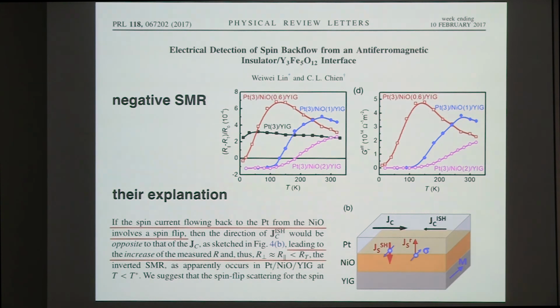Another thing is that we know them very well, they compete with us. So they actually at the same time produced the same result. Basically, this data tells you the same story, the same phenomenon I just showed. But actually, I want to criticize them, and very bravely in front of this camera. Yes. I think that this title and the explanation is far from satisfactory. The reason is that they think this effect is due to the spin reflected from this nickel oxide and YIG interface. And very clearly, they say that this is an electric detection of spin backflow from an antiferromagnet insulator and YIG interface, which is obviously not true.